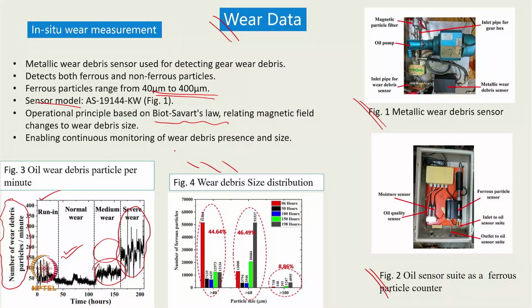Now this is another one, the size distribution. We find particles from 40 to 60 micron, which is something like 44.64%. Then particles of 60 to 100 micron, we find 46.5%, and particles more than 100 micron are a very small percentage. Now here we have given all the data after 6 hours, after 50 hours, after 100 hours, after 150 hours, and we operated until the complete gear failed at 198 hours.